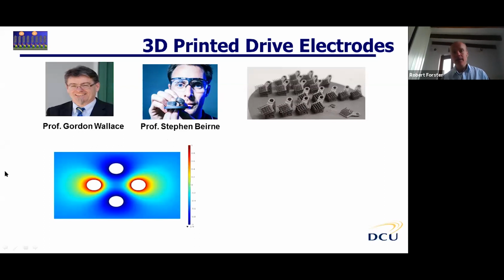For example, here what you're looking at is where 2 of those pins are positive, the positive feeder electrodes, and 2 are negative. We're trying to do COMSOL modeling of the field distribution within that pair of electrodes. And you can see that you get not just the linear decay directly between them, but interesting dips and troughs of intensity in the potential distribution of the electric field strength, depending on the configuration of the electrodes.